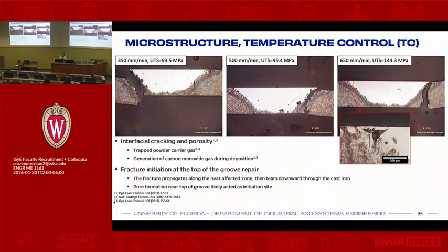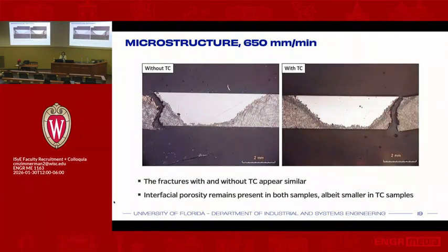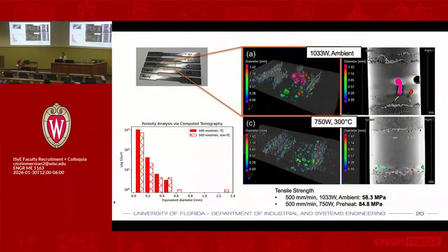So if you hone in even further on that speed, with and without that temperature control, you can see that in terms of the heat treatment, we can see a whole lot of changes in it. But with the temperature control, you do get less porosity. And this is a good example where you can actually see the amount of porosity that you're getting, especially when you're doing something with temperature control and without temperature control.